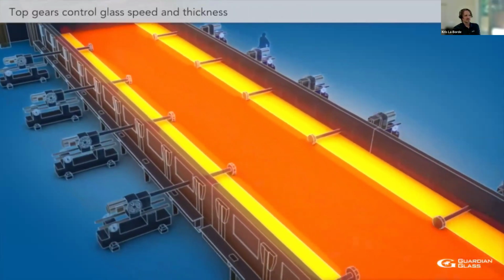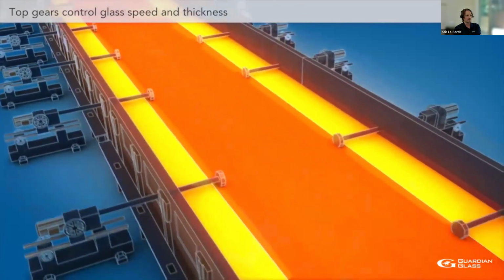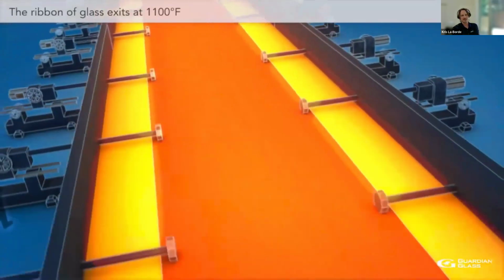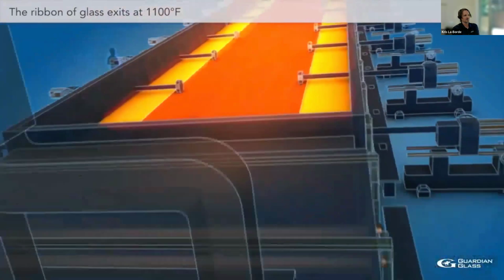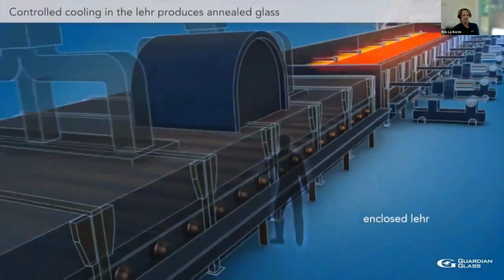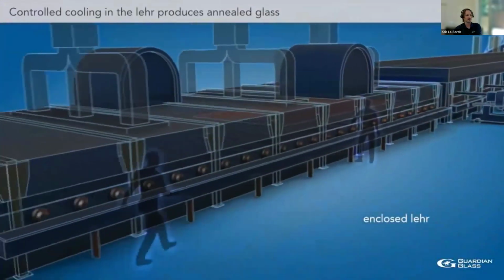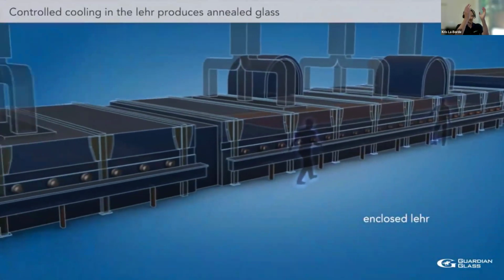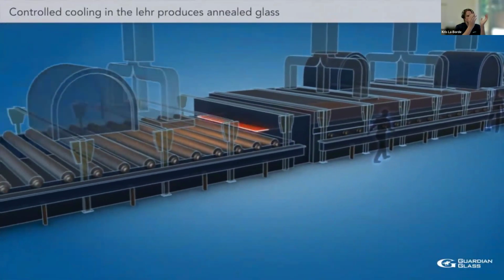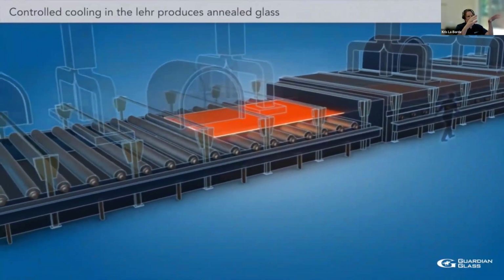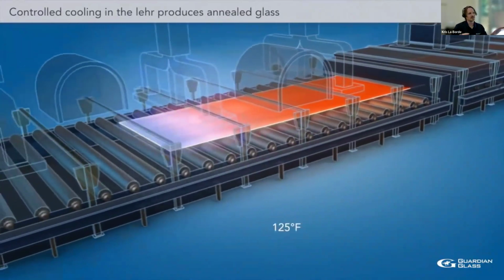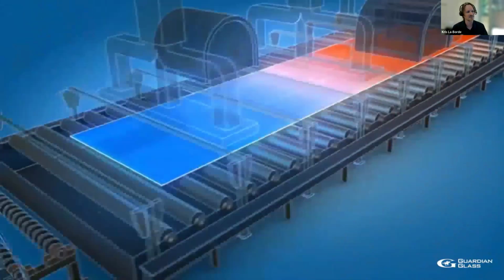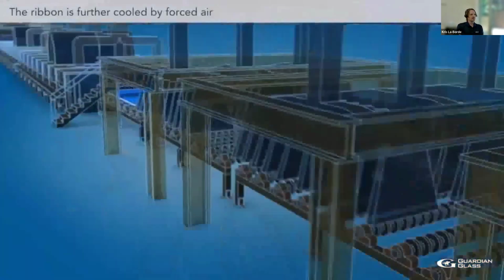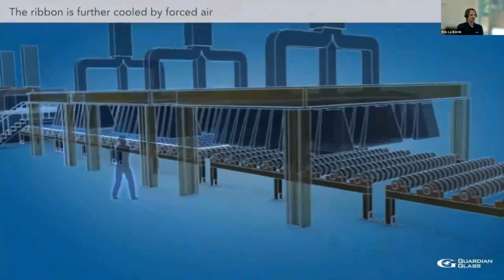If anyone specifies glass on this call, think about what is the most common thickness of glass that you see out in the real world. And you'll come back with 1/4 of an inch or 6 mil. 6 mil is what that natural density of glass will settle at. So if you let that molten glass settle by itself, it will always settle to 6 millimeters. So that's why there's a very good reason why most of the glass we see out there is 6 mil.